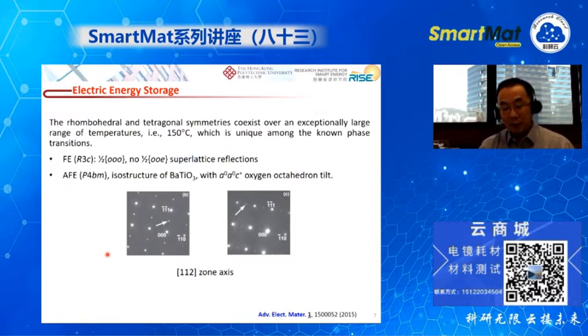Then in order to identify the different phases, we can use electron beam diffraction. And here is some methodology to identify the two different phases. For the ferroelectric phase, we can observe some superlattice reflections. You can see here we have a superlattice reflection, and the index is odd. You have 3 odd numbers. So for the ferroelectric phase, we can observe this superlattice at the 3-odd reflection index. And for the antiferroelectric phase, we can observe some superlattice spots at the index of 2 odd numbers and 1 even index. So this is a feature for the antiferroelectric phase.